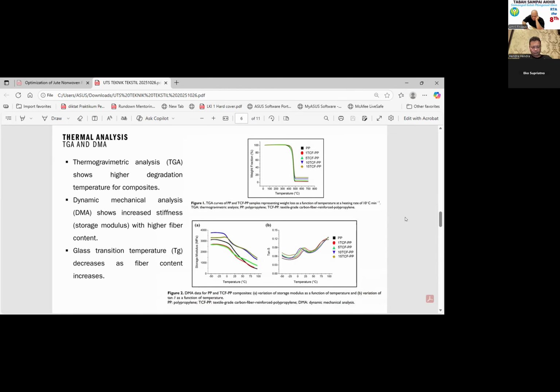It looks at how stiffness changes with the temperature. The storage modulus, which represents elastic stiffness, was found to increase with fiber content, especially at 10% and 15% fiber loading.